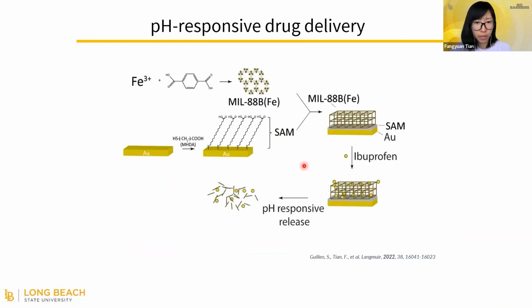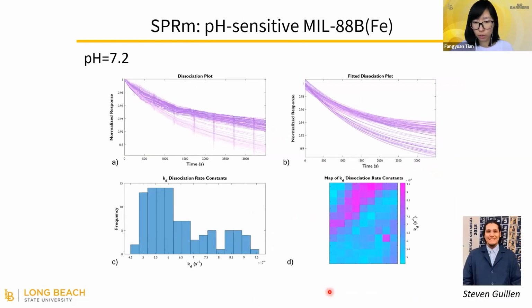But because our MIL-88B is quite biodegradable, we wanted to look at the pH responsiveness of this material and see if we can use it for drug delivery at different pH conditions. My graduate student, Stephen, did those experiments using surface plasmon resonance microscopy to look at the MIL-88B crystals under different pH conditions. It's under a flow of saline solution under different pH conditions. So this is the neutral condition. We could monitor the dissociation rate by looking at how the surface changes. This is the advantage of using SPRM.